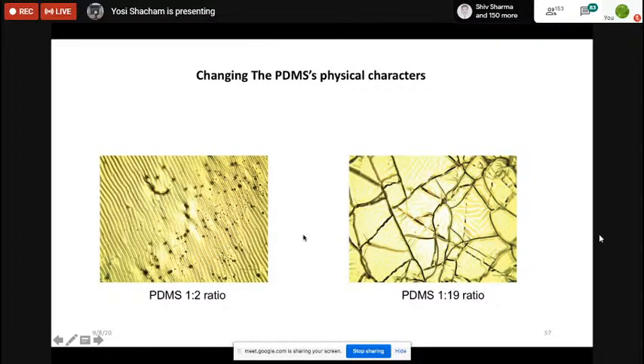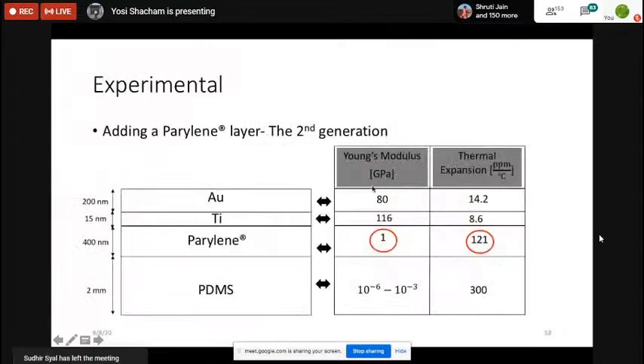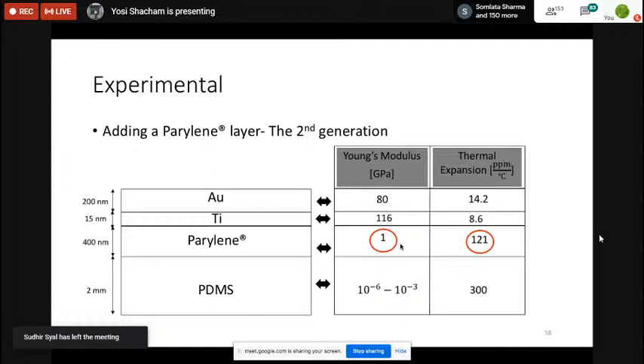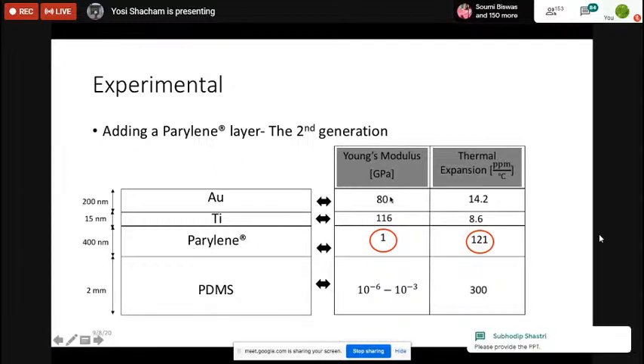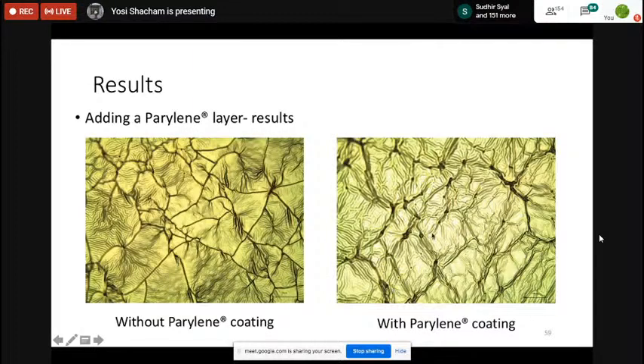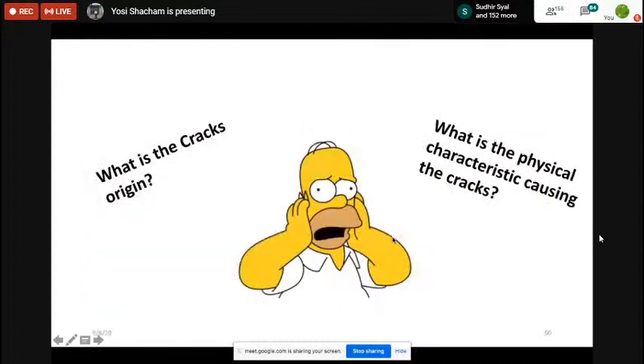So we want to understand why. How come this very soft polymer, with a Young's modulus of 10 to the minus 3 gigapascal, is breaking, making cracks in the gold, which is more than 10 gigapascal? So we took the structure. This is another experiment; we try to be smart. We put between our polymer and the metal another polymer called parylene, with a modulus between 1 and 8 gigapascal. Still got the same cracks. So we say we need to solve this problem.